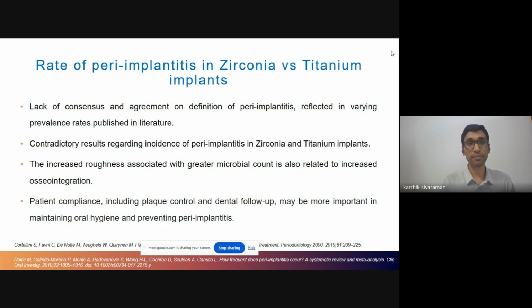However, there are certain differences or certain points which we need to consider here again. When we speak about peri-implantitis in the literature, we see a lack of consensus and agreement on the definition, and that has resulted in varying prevalence rates being published in the literature. In fact, there are contradictory results regarding incidence of peri-implantitis in zirconia and titanium implants. Like I mentioned, in the preclinical studies, there is evidence to say that there is less incidence of peri-implantitis in relation to zirconia. But when we look at the literature, even clinical aspects, we see contradictory results.